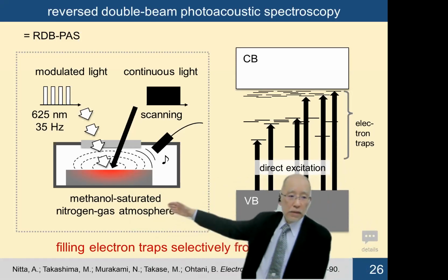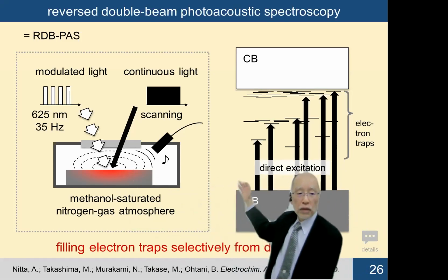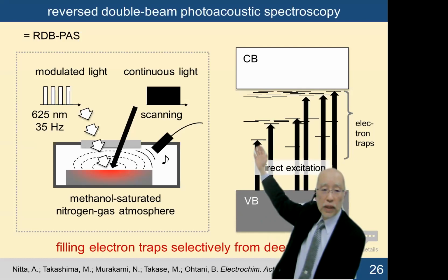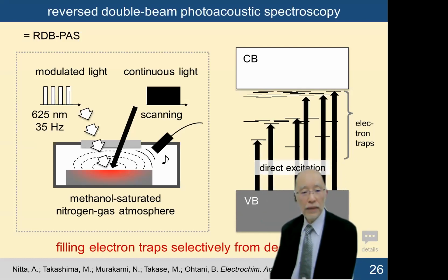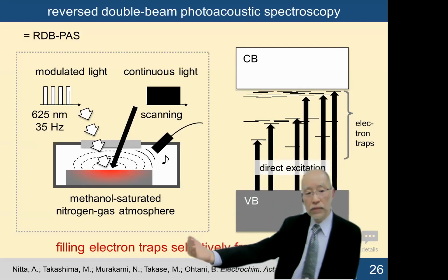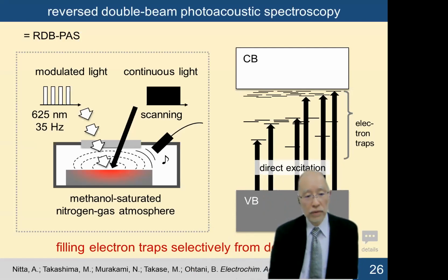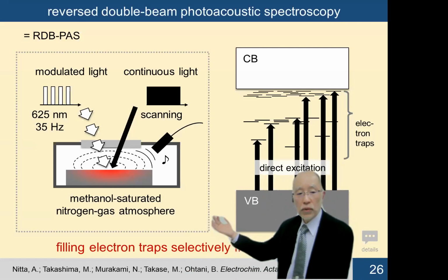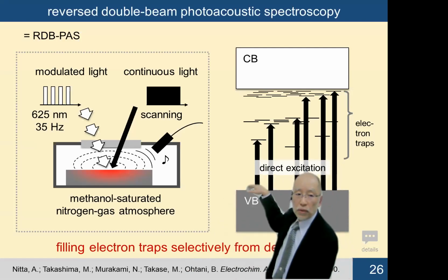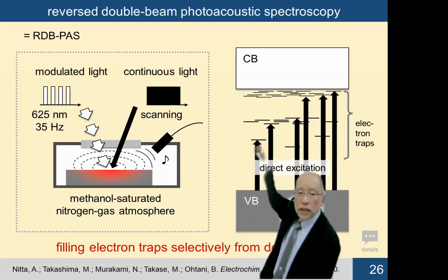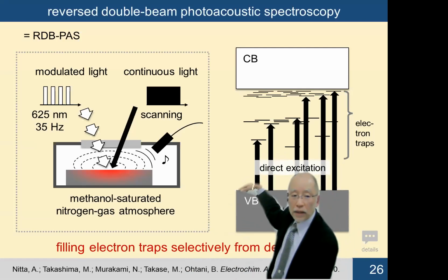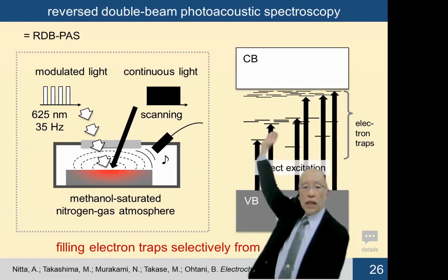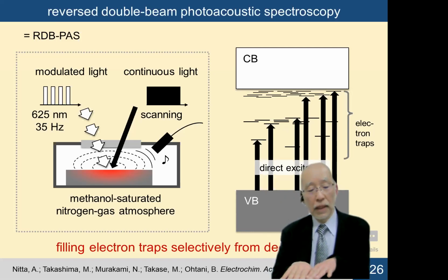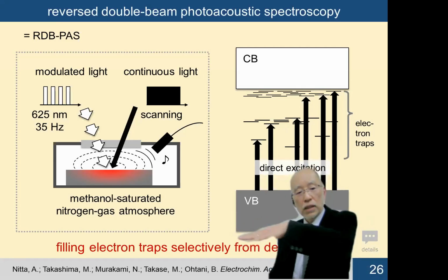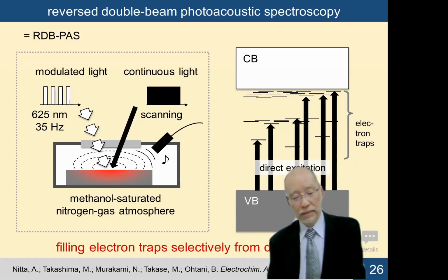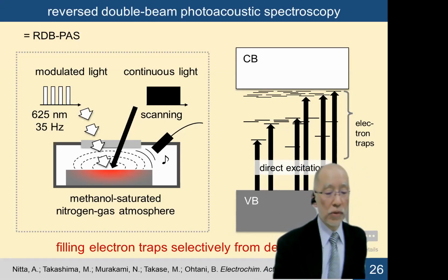And the secondary beam that is modulated is used for detection of the newly developed color due to electron accumulation in electron traps. And the excitation light wavelength is scanned from a longer wavelength region to a shorter wavelength region, that means from the lower energy side to the higher energy side. If the energy is low, only lower energy electron traps can be filled. As the wavelength is scanned to the higher energy side, the higher energy electron traps are filled then. So the electron traps in those materials are filled from the lower side to the higher side. So this is the principle of reverse double beam photoacoustic spectroscopy.